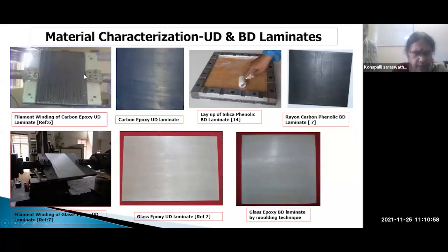Extreme left is the unidirectional fiber winding, filament winding of carbon epoxy UD laminate. This is the glass epoxy UD laminate. As I told you, between centers plate is held and it is wound. This is the laminate I got from this after curing. This is the laminate we got from this winding. This is the bidirectional fabric laminate of glass.